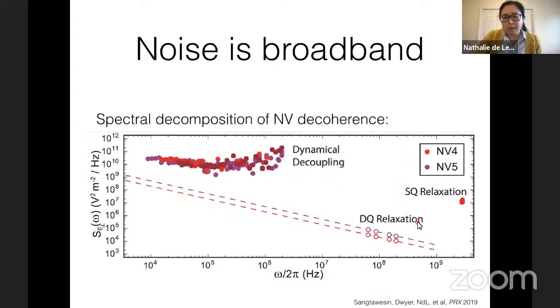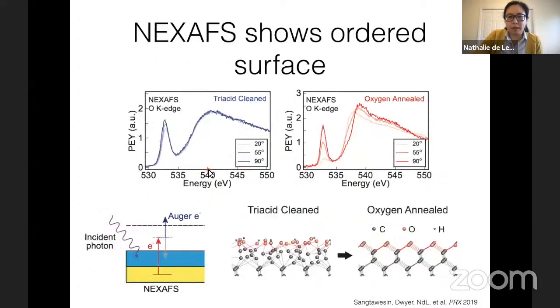If we put all of these pieces together, because I had a little bit of a sleight of hand, all of these different techniques are actually probing very different frequency ranges, and you have to take into account things like 1/f scaling. Then what we see is that this is what you expect from electric field noise, whereas this is a picture of what your magnetic field noise distribution looks like. And you can see that we have this very broadband noise source that is predominantly magnetic. Okay, so that's what we can learn from the point of view of the NV center.